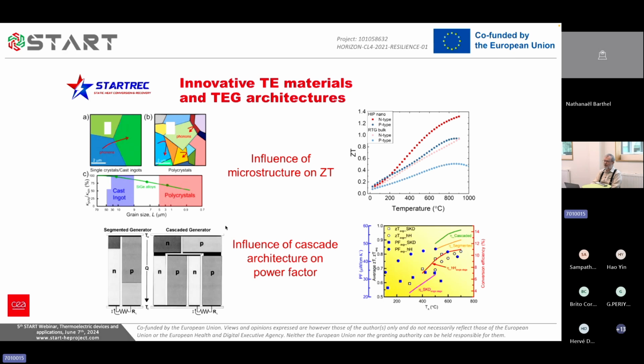And the cascading architecture. If you use a segmented generator, the conventional structure, or the cascade generators, so one on top of the other, then you see that the power factor increases so much and the conversion efficiency increases so much just by superposing. So the cold side of the first TEG is the hot side of the next one. So this is something that we are investigating.